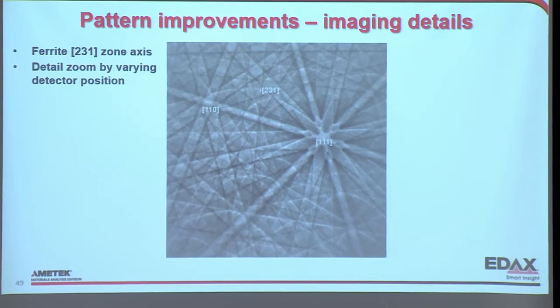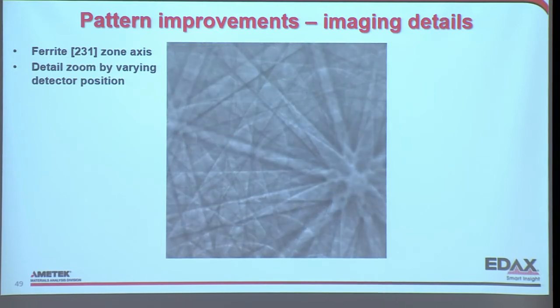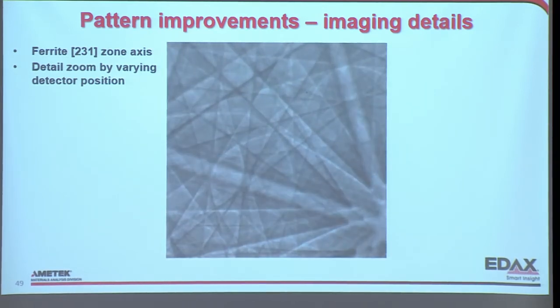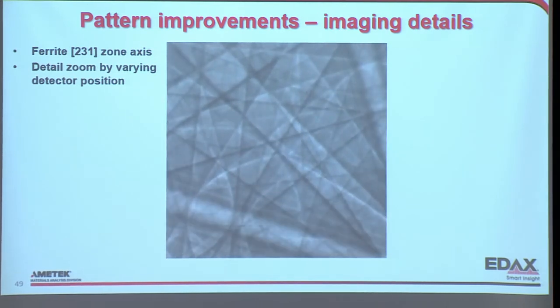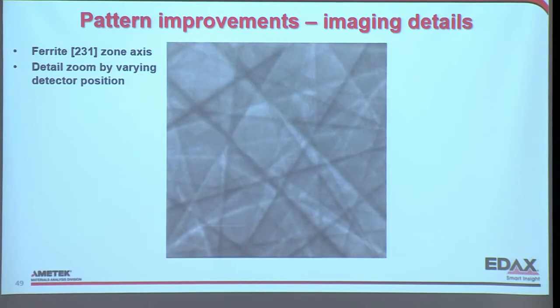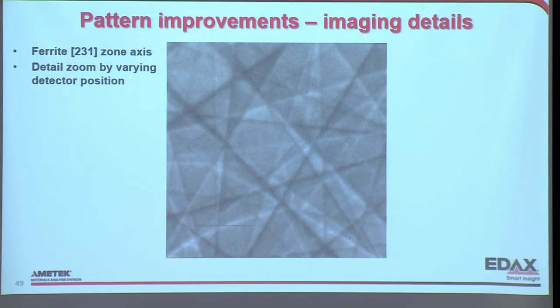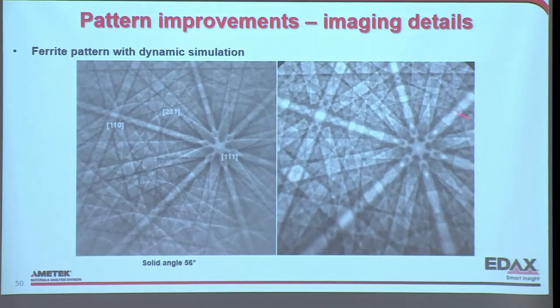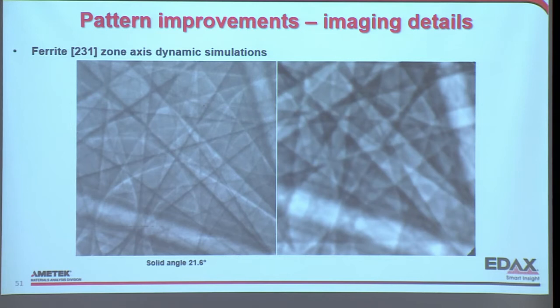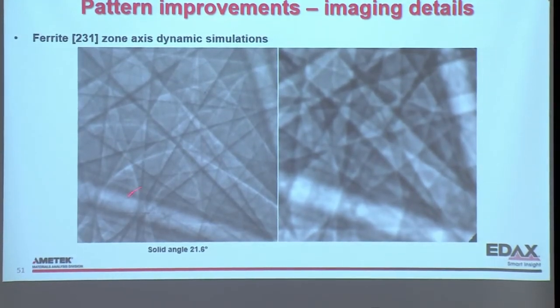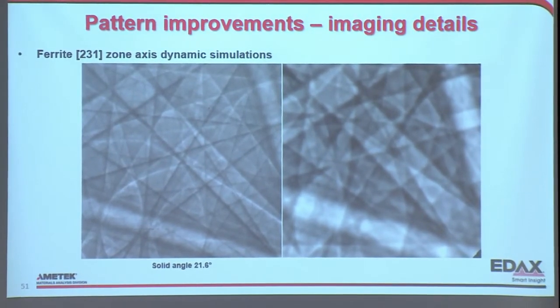Now I'm going to zoom in so you can really see the amount of detail here. So this is pulling the detector back is the way we're zooming in. It seems backwards, but we're getting more detail because we're reducing the solid angle. And even with the detector this far back, you can see detail. So it's amazing. This is actually a simulated pattern. And I'll come back to simulation, but we're getting as much detail as we get in the simulated patterns. These patterns have become helpful for really assessing how well our simulation's working. We're learning some things to improve the physics in our simulation models from these kind of patterns. And this is just zoomed up. Now we can do the simulation with more pixels to probably better approximate this, but the detail's amazing.